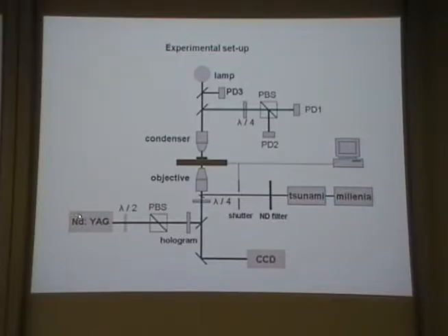So how does the typical setup look? Apart from having the setup for optical tweezers, I also have a Ti:sapphire femtosecond laser pumped by a solid state laser. I put this laser into my setup. It goes through the objective, which is high numerical aperture again, and then I control it by the computer. I control my stage by the computer. I have a pretty precise stage where the smallest step is only a few nanometers in XYZ. So when I want the laser to polymerize at a place, the gate is open, and when I move the stage and I don't want photopolymerization to take place, the laser is off. This is the shutter which I control from the computer.